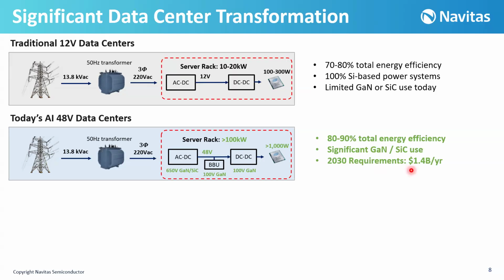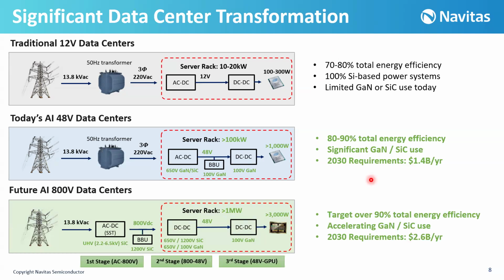Now let's talk about the future. In the future, we have the future AI 800 volt data centers. As you can see, we are replacing this bulky 50 hertz transformer with a solid state transformer AC-DC converter. So we are stepping down this high AC voltage to 800 volt DC, utilizing ultra high voltage silicon carbide at 2.2 and 6.5 kilovolts. And then we are using a BBU utilizing 1200 volts here. Then in the server rack, we are stepping down again to 48 volts, with a DC-DC converter instead of an AC-DC converter, with 650 volt and 1200 volt silicon carbide and 650 volt and 100 volt gallium nitride.